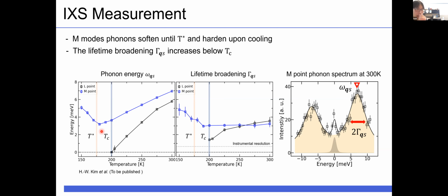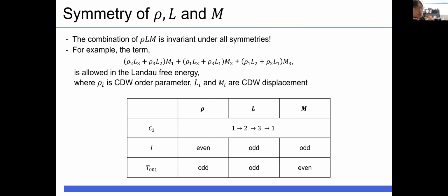And the interesting thing is that the lifetime broadening gamma of the M point increases below the critical temperature, which means that the M phonon starts to couple with something below the critical temperature. So what could couple with the M phonon? It's natural to think of the CDW order parameter and L displacement, because they become non-zero below the critical temperature. And if we consider this coupling, we can explain chirality using Landau analysis.